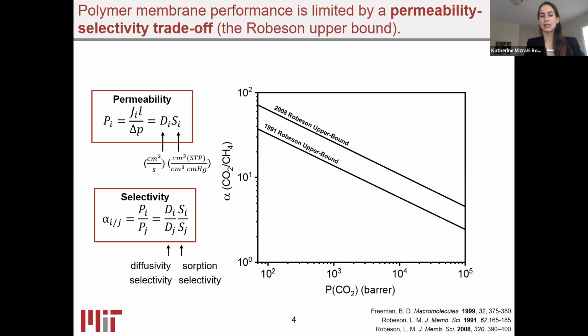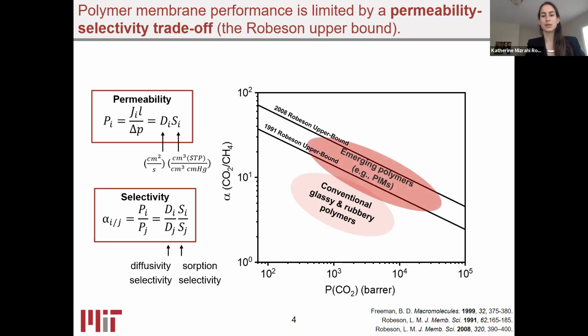In 1991, Professor Robeson actually plotted a log-log plot of selectivity against permeability and found that there was an inverse relationship in the performance of materials to that date, and that there was a limit or an upper bound for these materials that they would not go above. So conventional glassy and rubbery polymers fell below the upper bound. And then in 2008, this was updated with emerging polymeric materials, where these fell closer to the upper bound, but they still had limited performance. So typically researchers aim to find and develop materials that have increased permeability and selectivity combinations.